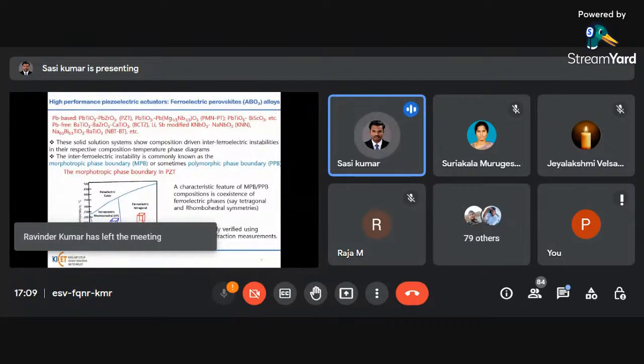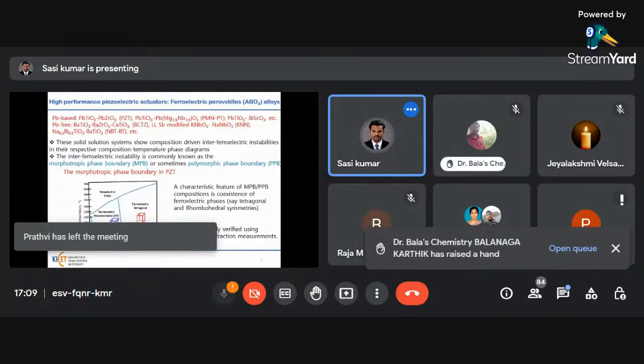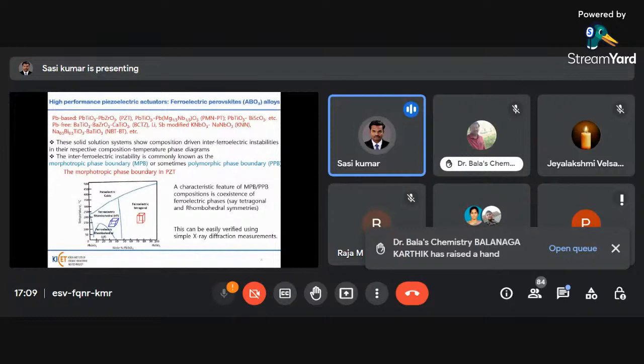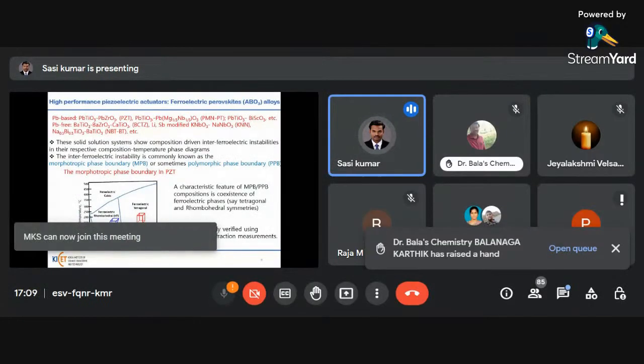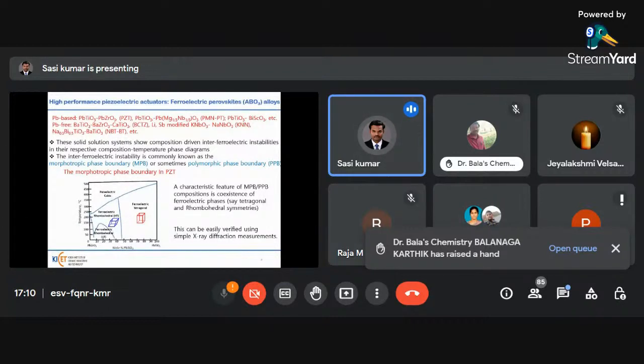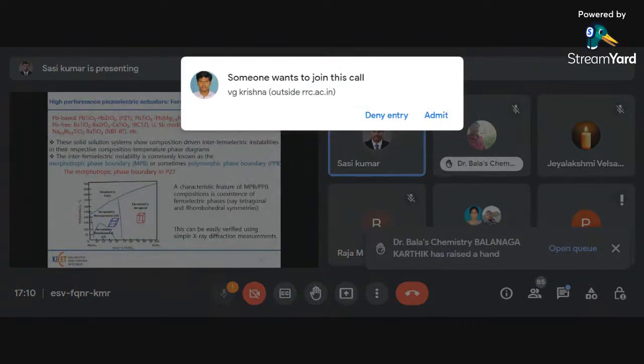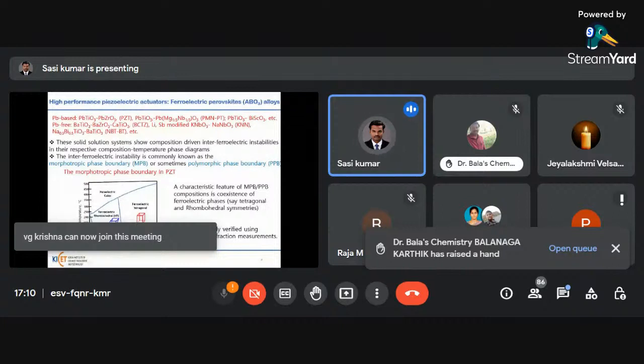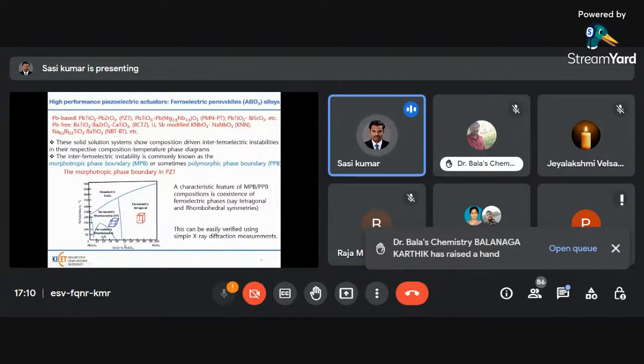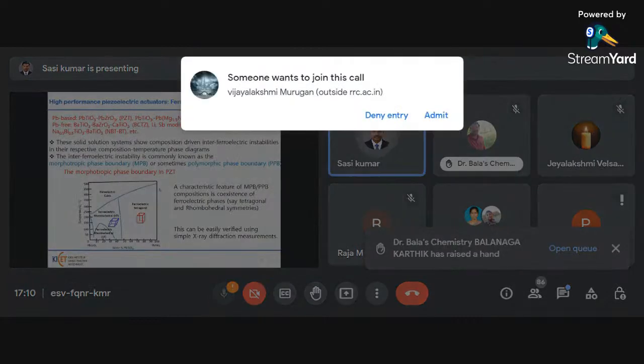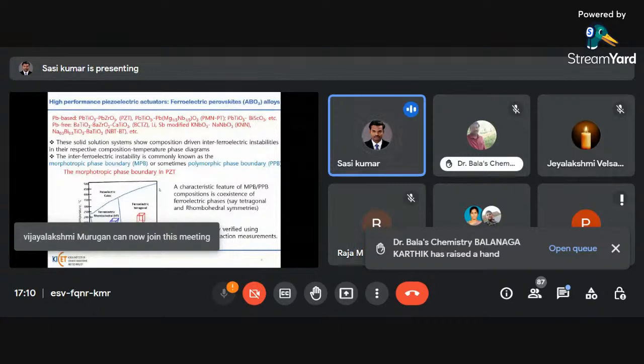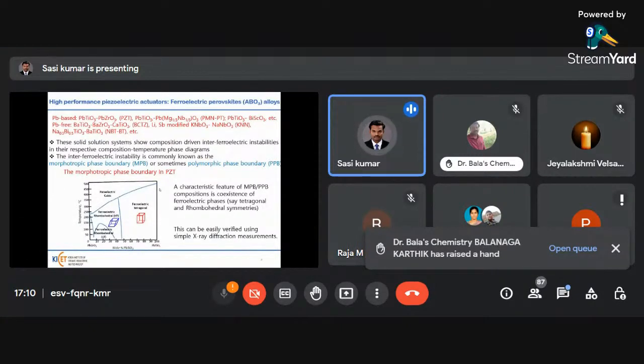Okay, here is the morphotropic phase boundary of PZT. PZT means lead zirconate titanate samples. So what is the morphotropic phase boundary? The solid solution system shows composition-driven ferroelectric instabilities in the respective composition. At some particular ratios, for example, when x is equal to 0.45 to around 0.5, the sample possesses two different structures existing in one material. One is a rhombohedral structure and another is a tetragonal structure in one particular composition. It is the morphotropic phase boundary of these PZT samples.